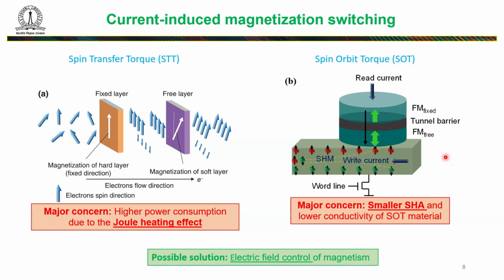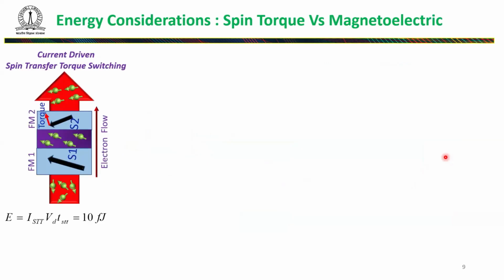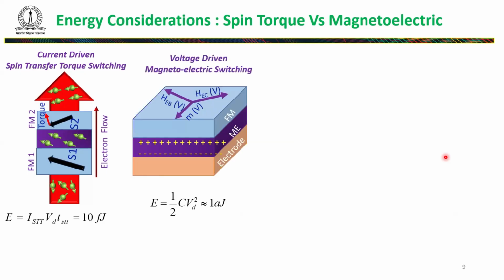So what are the other opportunities? One way is: can you not switch the magnet with current, but rather with the electric field? And this is what I'm going to talk about today. If you use current-driven spin transfer torque switching, the energy requirement comes to around 10 femtojoules for operating 1 bit. But if you make a technology based on the magnetoelectric effect, then the energy requirement is reduced to 1 attojoule. So it's a big gain in terms of energy consumption.